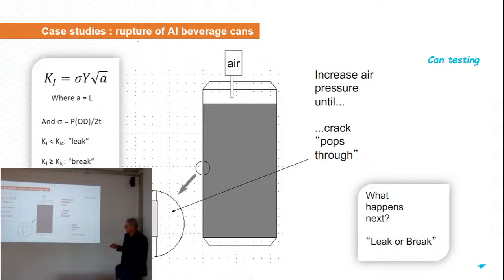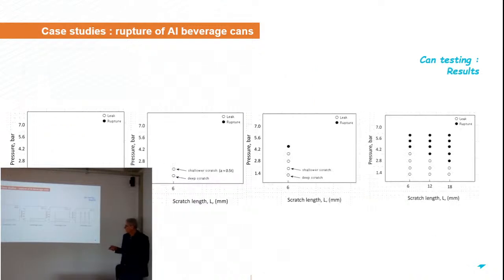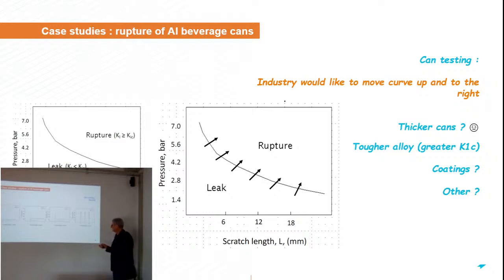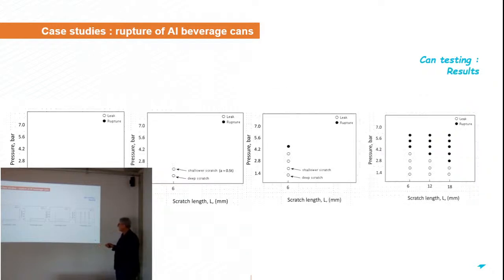If the stress intensity factor is lower than the toughness of the material, in this case you have a leak. If the stress intensity factor is greater than the toughness of the material, in this case you have a break. Okay. So with this test here, where for a given scratch length, here 6 millimeter, we increase the pressure and look whether we have a leak or whether we have a rupture. And you can see that at this level of pressure, we have only leak. If you increase a little bit the pressure, you can get leak, and then leak, and again leak here, and then the fracture of the material.